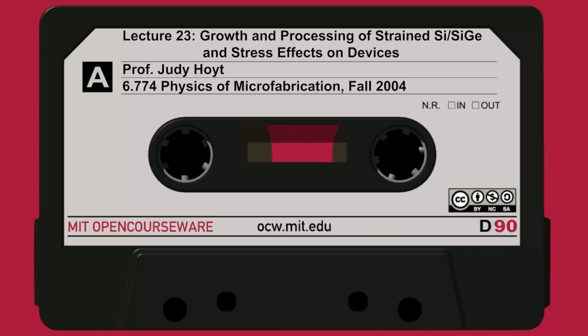So I refer to the fact that we have this strain, and I guess I should have introduced slide 8 a little bit earlier, but this just gives you a ball and stick picture of what we're talking about. The ball and stick up in the upper left is meant to represent cubic silicon. It has a lattice parameter of about 5.4 angstroms. It's the diamond cubic structure, but nevertheless, it has a cubic symmetry to it. In X, Y, and Z, those 3 dimensions, the lattice constant is the same number. Cubic germanium is larger, same kind of diamond cubic structure, but larger by about 4%.